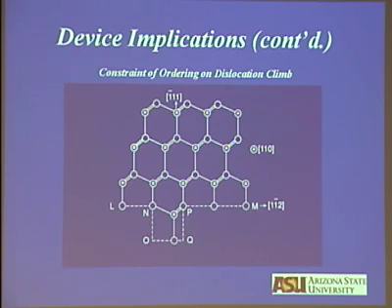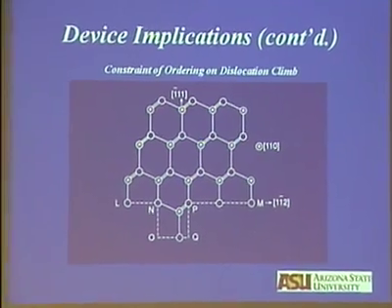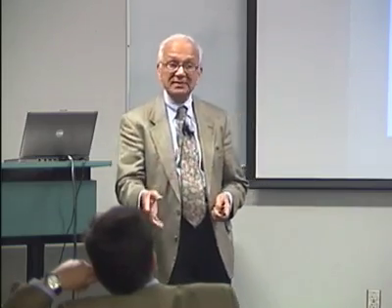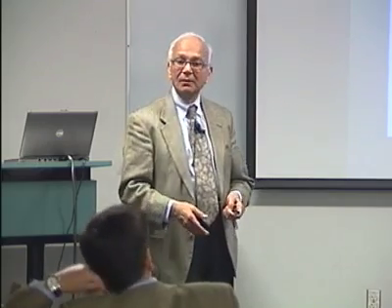So what it tells you is, if you are dealing with light emitting devices which degrade by the multiplication of dislocations, these things can't happen easily. You will prolong the life of your devices. And that's what you observe. Indium gallium arsenide phosphide on indium phosphide, even though it's more defective, is phase separated. It has a much longer life than the gallium arsenide based devices, which are more perfect because they are not phase separated.